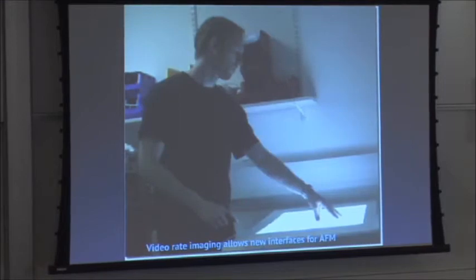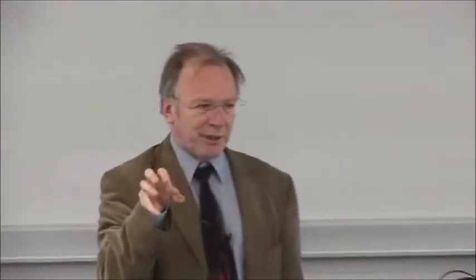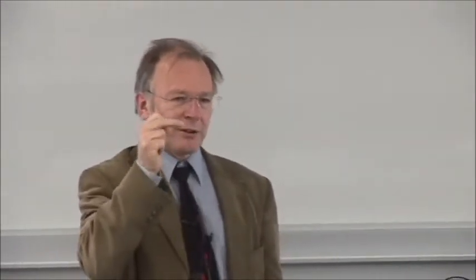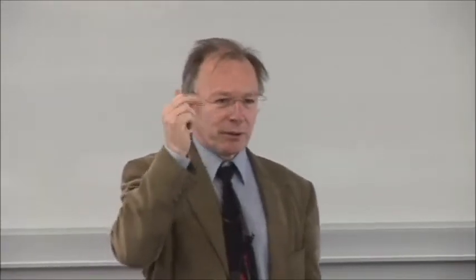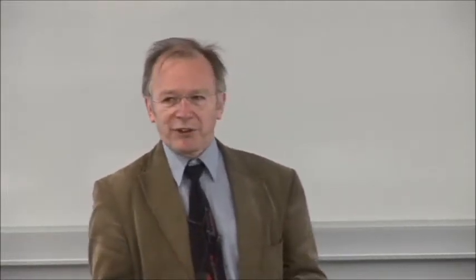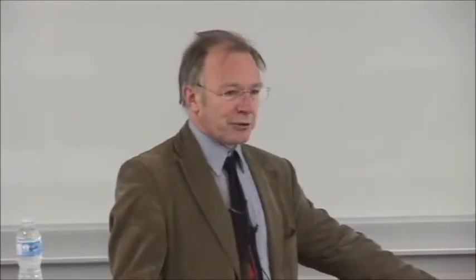This is, what can you do if you've got video rate? What's different? Well, you can make a different interface. With all normal AFM, you watch the line scanning, you set the parameters, the scan speed, the feedback loop, and so on, and it captures the data, and you can go and have a cup of coffee or whatever, and come back later. But if you've got a video rate, you can interact with that instead. You can actually use, in this case, a multi-touch table to control.